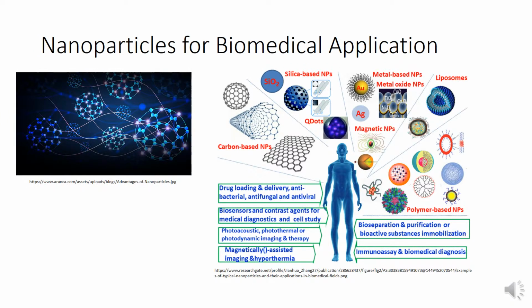So, nanoparticles have the ability to carry large drug payloads while also providing an accessible site for ligand attachment to allow for specificity. By altering the chemical and physical properties of these materials, such as shape or elasticity, their in vivo properties can be drastically altered. The problem, however, arises in that the vast majority of these technologies under development only offer low aspect ratio materials, that is, an aspect ratio under 5.